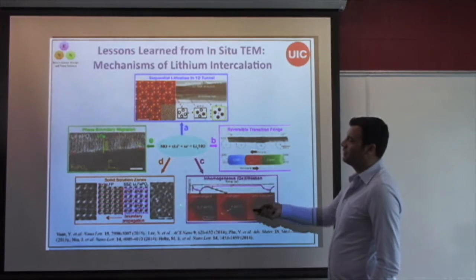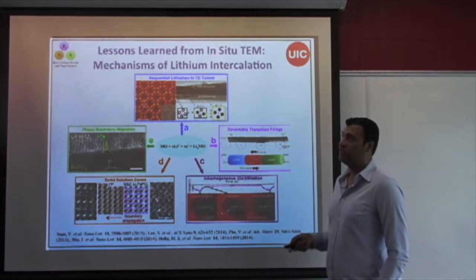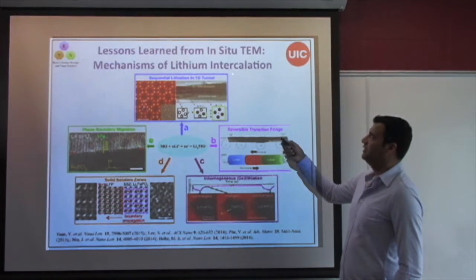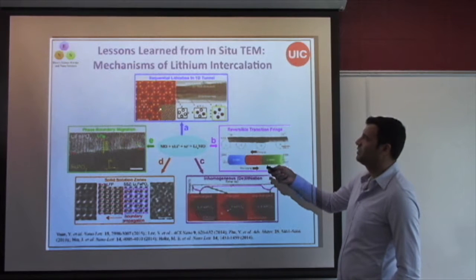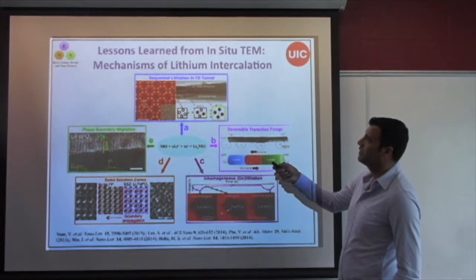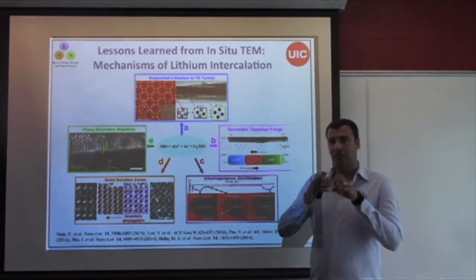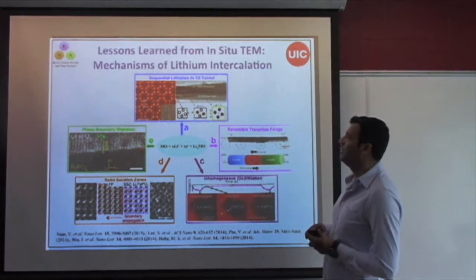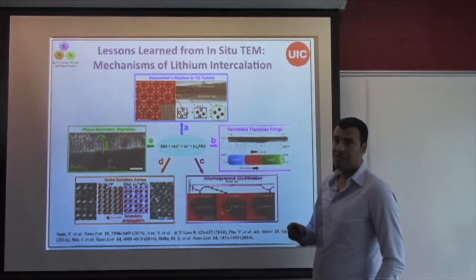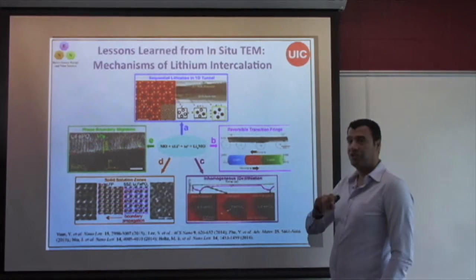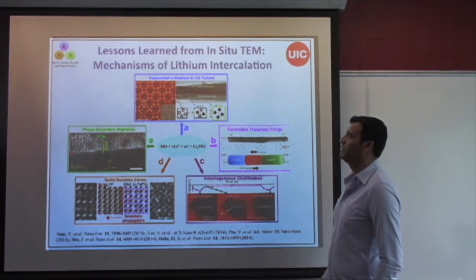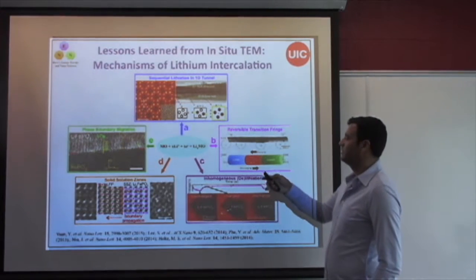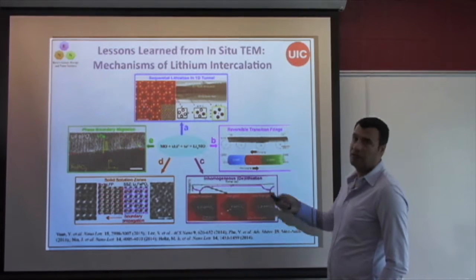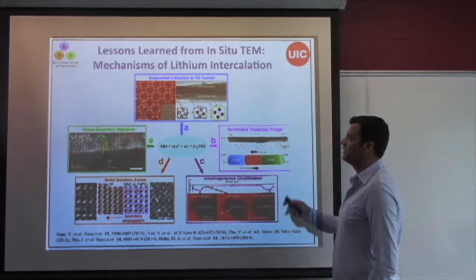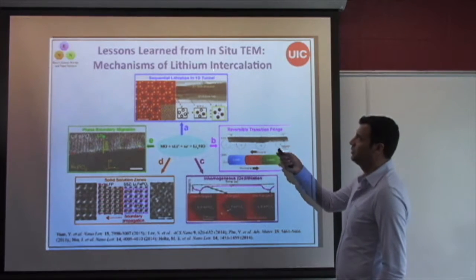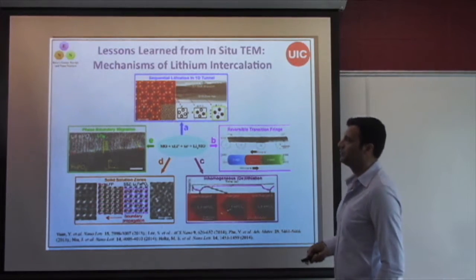A similar sort of summary we have done on looking at mechanisms of intercalation. One of my PhD students did a couple of years of research on looking at tunnel-based materials, looking into what are the preferred insertion locations for the lithium within these tunnel-based systems, and what drives a Jahn-Teller distortion mechanism within these tunnel-based materials. Specifically, we look at manganese oxide materials.